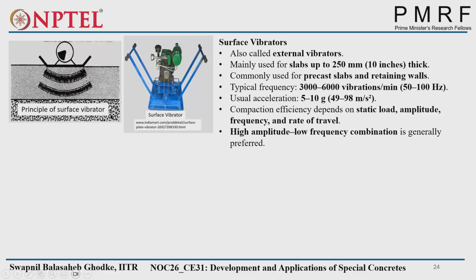Now this is also an external vibrator. Here the limit is slabs up to 250 mm thick. Commonly used for precast slabs and retaining walls. For retaining walls, it is more popular compared to the precast one. It runs at 3000 to 6000 vibrations per minute, 50 to 100 hertz frequency, and 5 to 10 g usual accelerations.